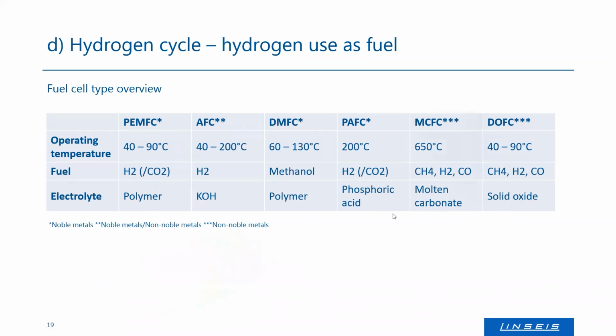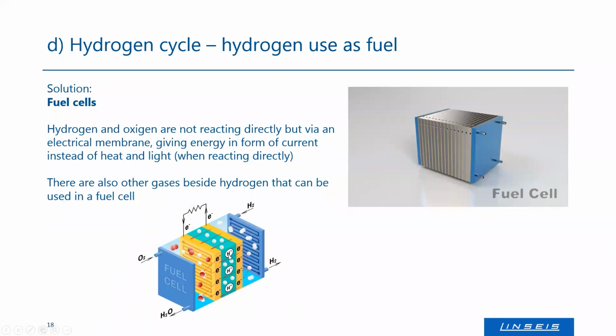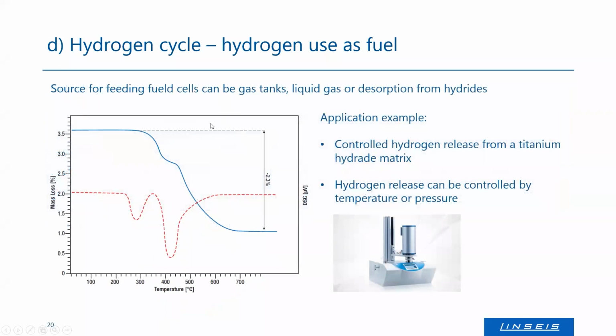And of course, as this is a complex structure, we are involved in investigating these membrane materials. We're doing a lot of thin film analysis on that, measuring thermal conductivity, how much the heat that you get during the process has an influence on that, doing thermal stability tests, and doing also aging experiments with these membrane particles with our thin film analyzers to measure how long they last under certain conditions and when aging takes place and when not.